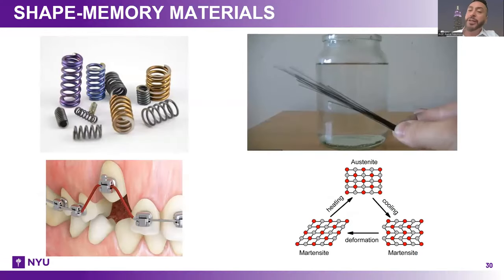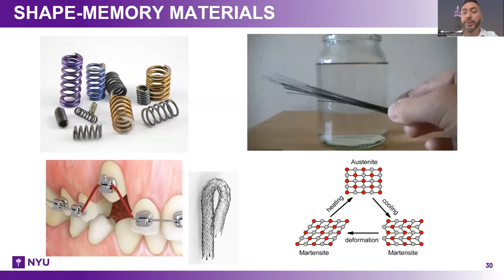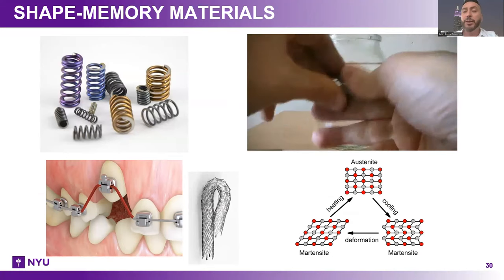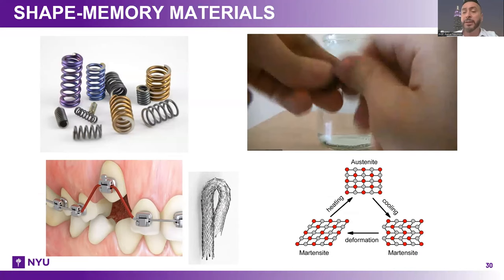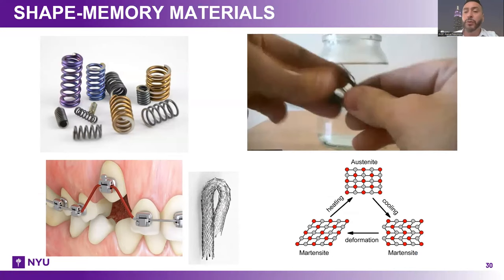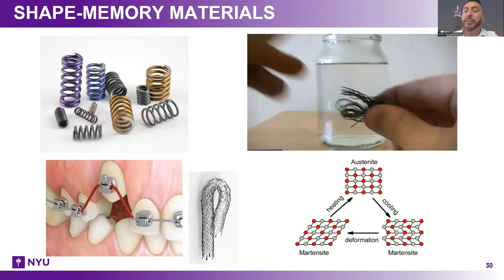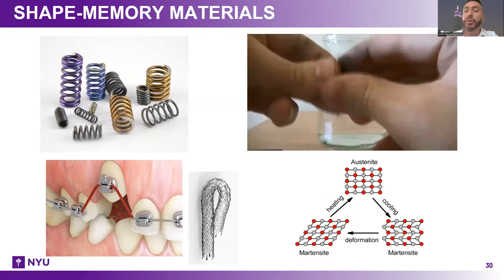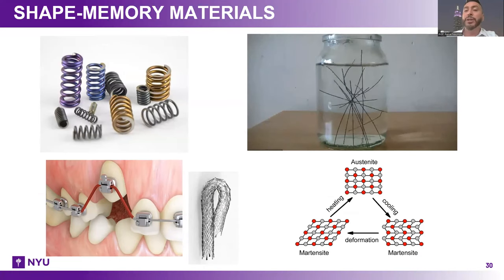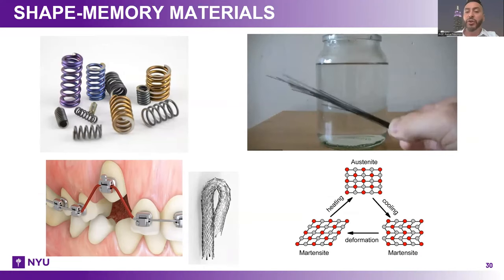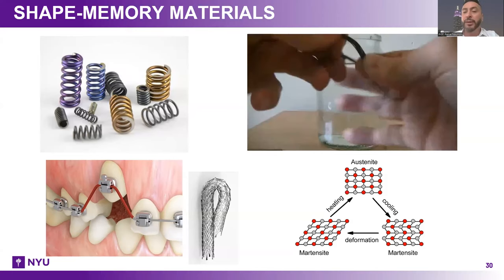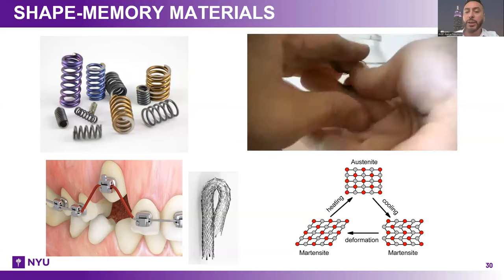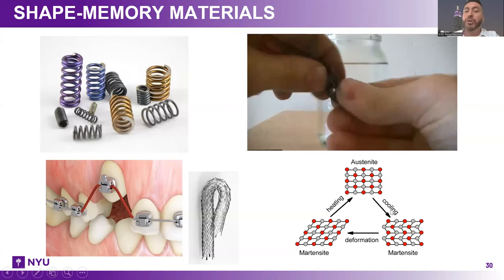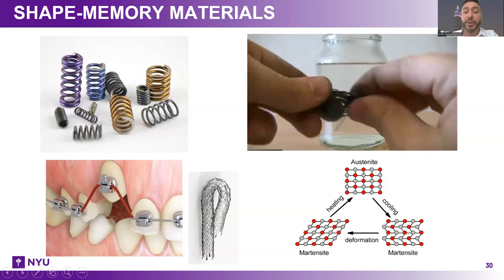Now, one of the most interesting developments is the so-called shape memory. For some of you that are not familiar with this term, shape memory is a property that was discovered back in the 70s, last century, for materials, specifically metal alloys, and of course also for polymers, where you basically mechanically deform the material and then you change the temperature. And when that happens, the material recovers its original shape. So it kind of memorizes the shape. And we were thinking, can we do something like this? Because this is a pure phase transition, as you can see here from the plot below the movie. Can we do something like this for crystals? Yes, the answer is we can.